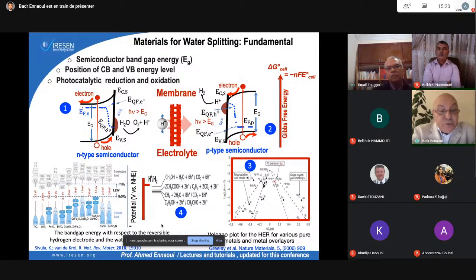What I show you here is all these reactions, what I showed you in the beginning, you can situate them on the electrochemical scale here. And you can know which reaction can occur at which potential. And also you can prepare different kinds of material, titanium oxide, tungsten oxide, etc. All these materials are good candidates for water splitting. And unfortunately, you see all these chemical reactions are close to each other, which makes the challenge much, much bigger. And the research is very complicated here.